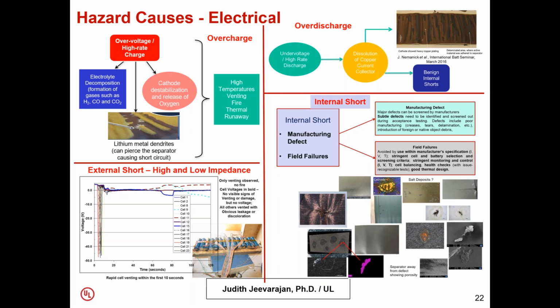But in some cases, you have subtle over discharges where you're just going slightly below the manufacturer's specification through your cycling process. At this point, when lithium ion tries to intercalate into the anode, it might not be able to do it because copper has spread on the anode surface. And so it deposits as lithium metal. In those cases, depending on the extent of the over discharge and the cycling, and of course the temperatures too, one can have a sudden thermal runaway, and people will not understand why it happened unless they have the right data collecting capability, which they can analyze later.